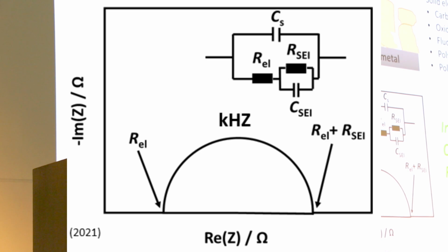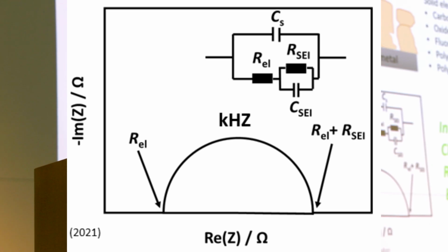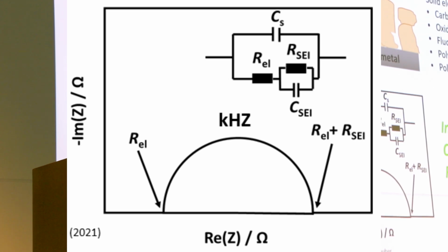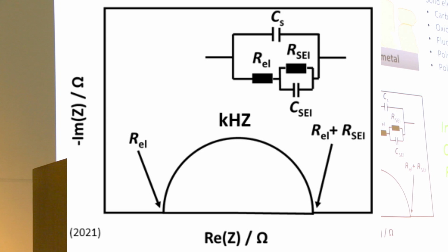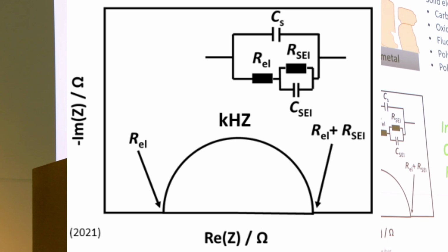We can work close to OCV, meaning that we can apply very small potentials and still look at what is happening with our material. And in this case, impedance is a quite nice and useful method because we always end up with such a semicircle in a Nyquist plot, which is in the kilohertz range. So we directly, in a way, see the SEI contribution if we have a symmetric metal cell. When we have this SEI contribution very well defined in a semicircle, what we could do is either look at the evolution of this resistance in time or look at the activation energy of this process.